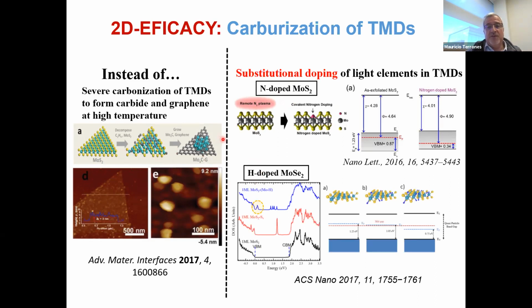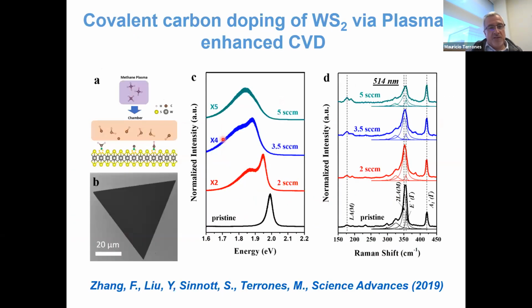But that's fine. What we did is we grew the tungsten disulfide monolayers, and then after growth, we do a plasma treatment at high temperatures with methane. We're trying to create some sulfur vacancies and then see if we can insert carbon-hydrogen units into these sulfur vacancies. So this is the result of the PL. Well, let's go to the Raman first. So this is the pristine material. I showed you the tungsten disulfide with the vanadium case. And this is the flow rate of methane here.